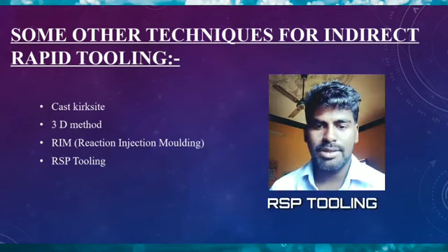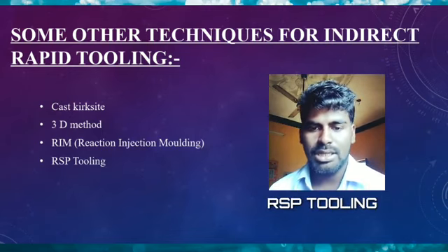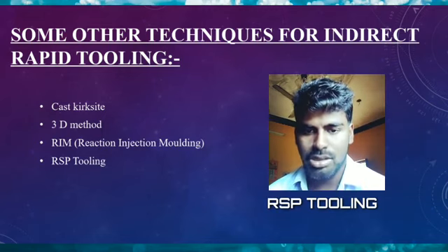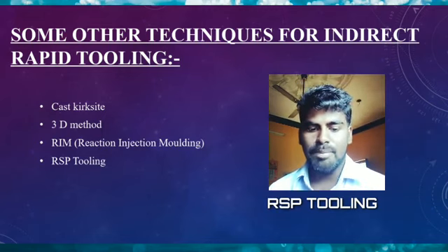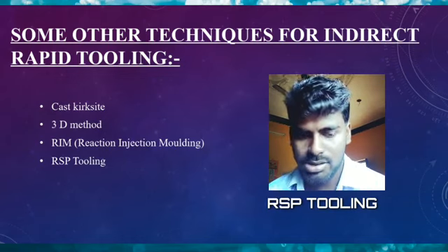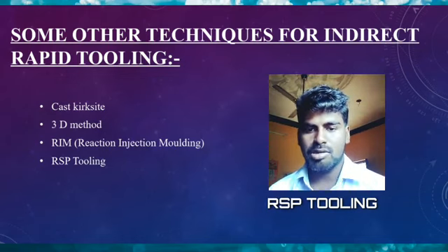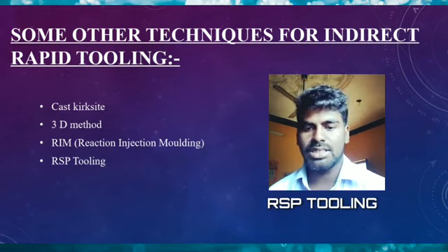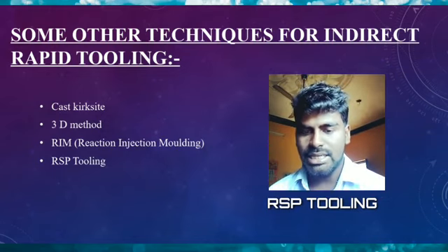Tooling. RSP means rapid solidification process. First, we create a plastic mold using SLA, stereolithography, and then we make a mold with either epoxy tooling and spray metal onto it. In most cases, ceramics are used as the main material. We atomize the metal down to a smaller size, microns. When the metal hits the ceramic, because of the small size of the droplets, they freeze very quickly and the rapid solidification process occurs easily. The process results in an extremely fine grained structure, and alloys generally stay in solution, with very little internal stress.